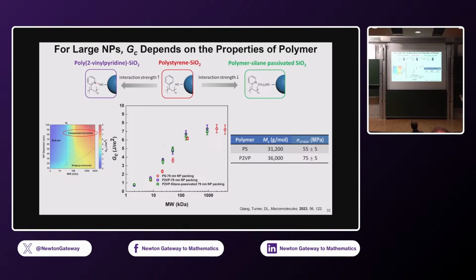Okay, and we can also weaken the interactions between poly-2-vinyl pyridine and silica by doing passivation. And what you see is that there's some difference, but not a significantly large difference. In fact, what we learned is that if we go to a polymer that has very, very high intrinsic toughness, that gives you the highest toughness for these materials. And that, again, is because we believe these remaining entanglements within these pores are playing a very important role in toughening these materials. Do I have another 3 minutes, or should I finish?